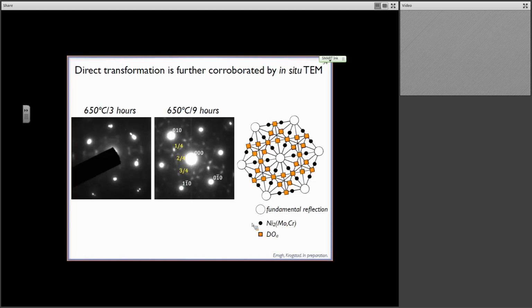And to ensure, so 48 hours, fine, we know the diffusion kinetics are accelerated, perhaps 48 hours is too long. We went back and did some in situ treatments. Perhaps we just smashed all of those different steps into 48 hours, and we didn't see them because we started with such a long heat treatment. Well, we did in situ heat treatments, and we found none of that evidence. Trust me, based on the analysis here, or you can look very closely, all the reflections that we see and the transfer of intensity between the sublattice reflections are associated only with the equilibrium D0a phase rather than the expected nickel-2 moly phase, which is the metastable precipitate.